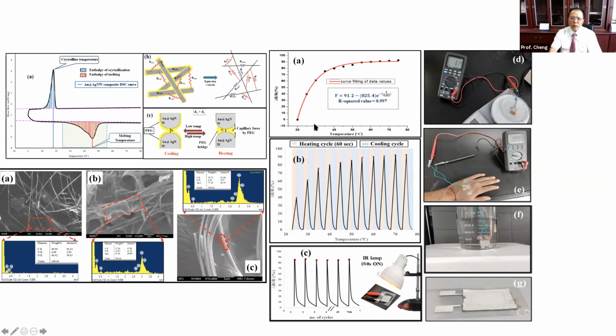So we can measure the temperature. When the temperature increases, the resistance also changes. So you can see the delta R by R. This is quite sensitive from 20 degrees to 40 degrees. This part is very good for human body temperature. And from the SEM picture, you can see the silver nanowire is coated with the PEG. So this is why our sensor is so sensitive.